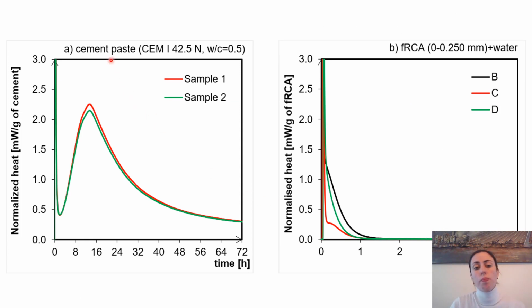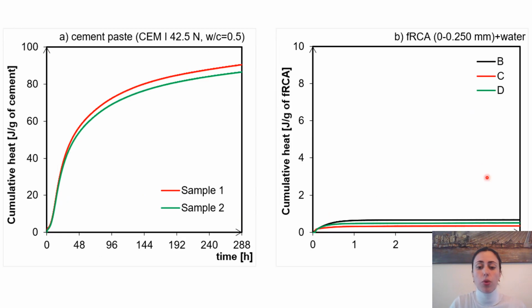Compared to the cement paste, where we have a very characteristic peak for the formation of hydration products after 8 to 16 hours, the heat release for the recycled sand and water has been basically 0. And then when we plot cumulative heat on the scale of 288 hours, we can see that compared to the cement paste, the cumulative heat of any reaction that could happen between the water and the fines, meaning the fines below 250 microns, is very, very low.